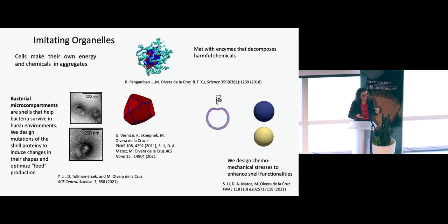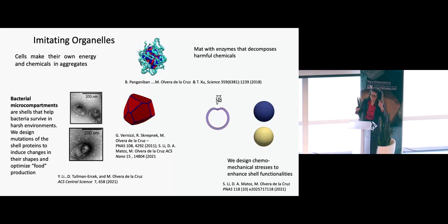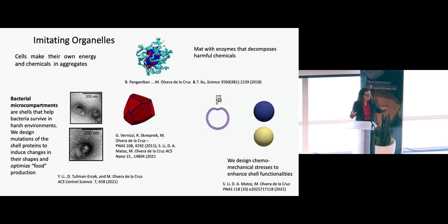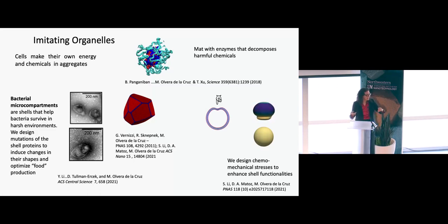You can see how smart the design is: the rigid red part can absorb harmful components, and the bending blue part is more open and lets them infiltrate inside to be converted, then they can exit. This is an example of what theory combined with experiment can achieve. We can even make vesicles ourselves—polymer vesicles called polymersomes—with a catalyst on the surface. We have shown that if you mechanically poke these materials, you can induce an autocatalytic chemical reaction and change their shapes. In biology this would be called chemo-mechanical stresses—triggering chemistry that adds components and drives change.